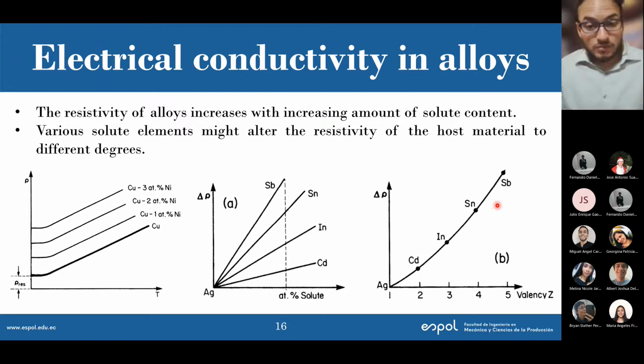Tin obviously has a valence of 4, even higher resistivity. Antimony, valence of 5, even higher resistivity. And this is just comparing silver, a monovalent metal, and you all know monovalent metals have high conductivities, with adding other elements. Especially look at the bivalent, trivalent, or metals that have 4 or 5 valence electrons. It increases my resistivity, so it decreases my conductivity. And you can see here the effect, for example, for antimony.